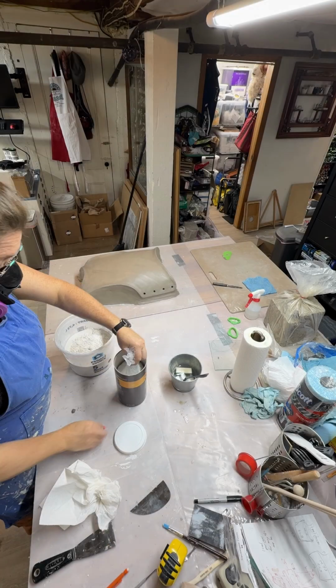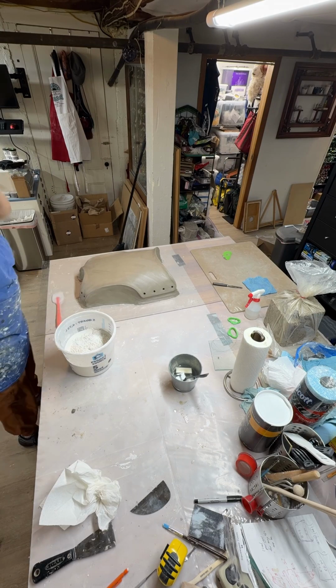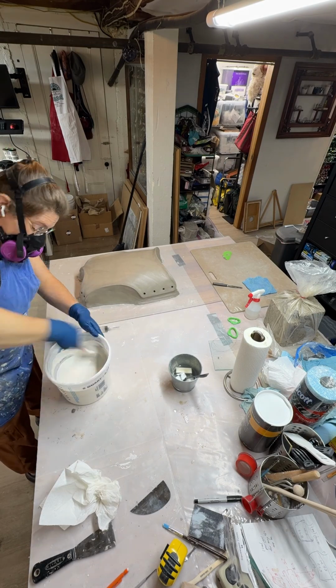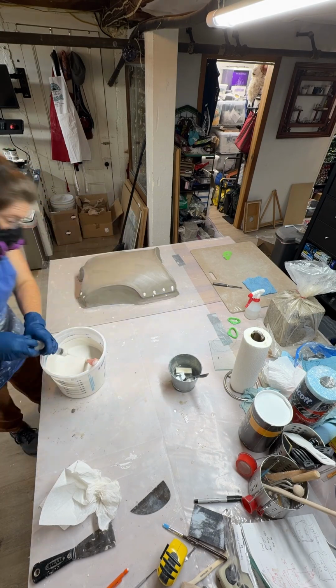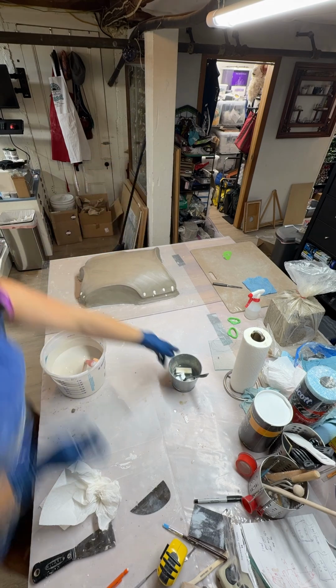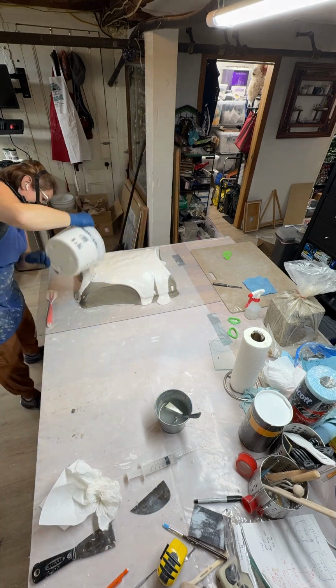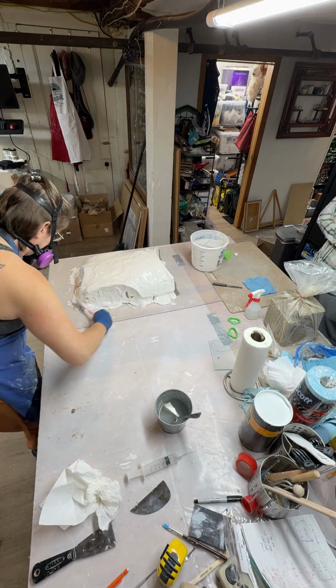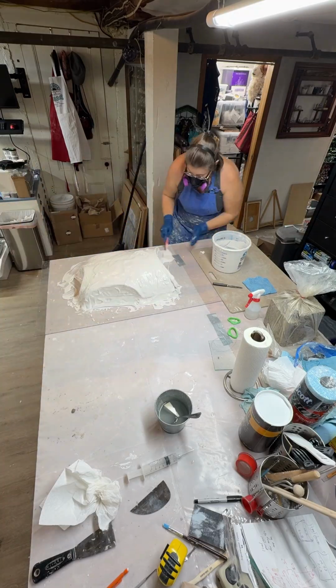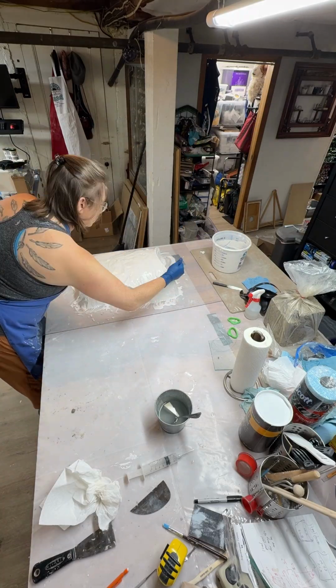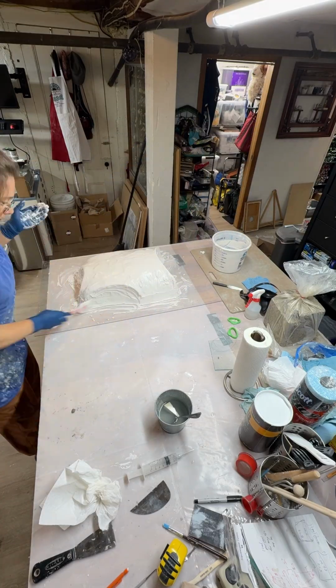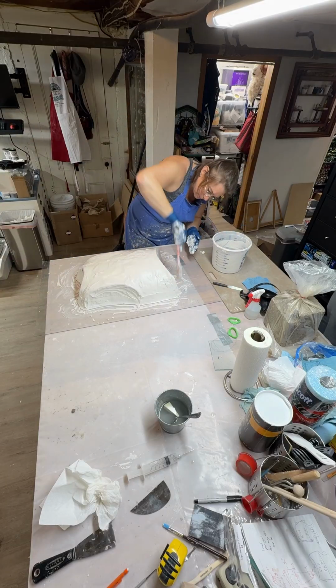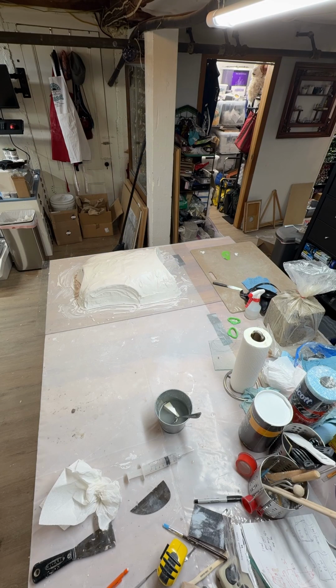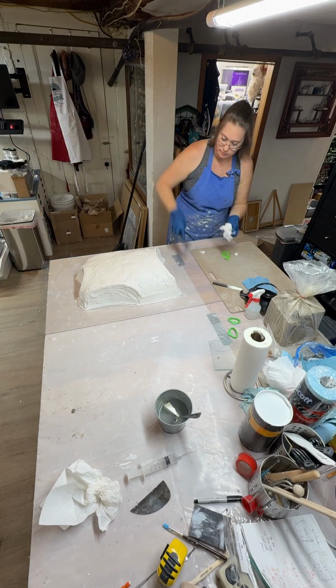The face coat is a 50-50 mix of potter's plaster and silica flour. I start by filling in the tie holes with the plaster mix using a craft syringe, and then I quickly coat the whole surface, using a spatula to move the plaster around and make sure the whole thing is covered. It's meant to be a thin coat that captures all of the details of the clay model. A quick cleanup of the board around the piece, and we are ready for layer 2.